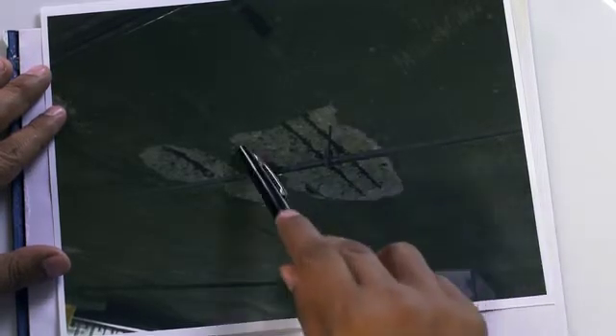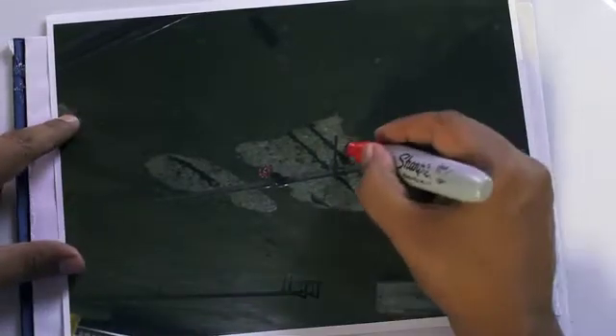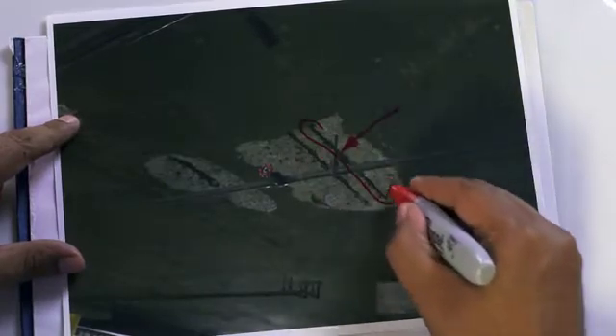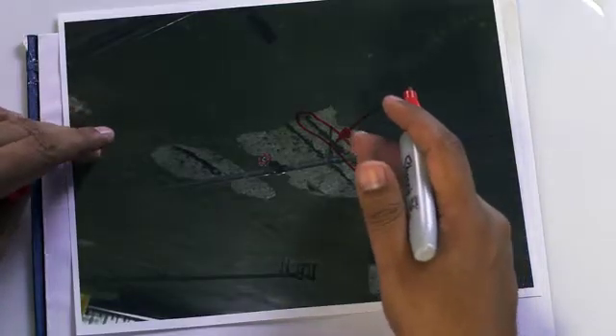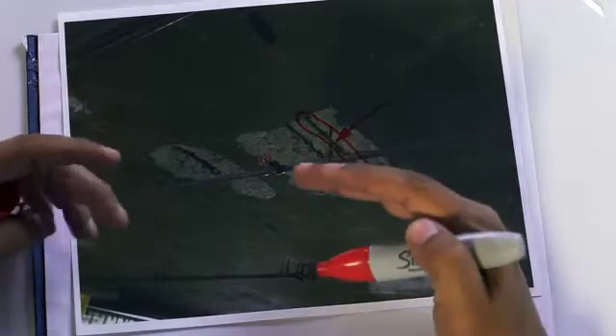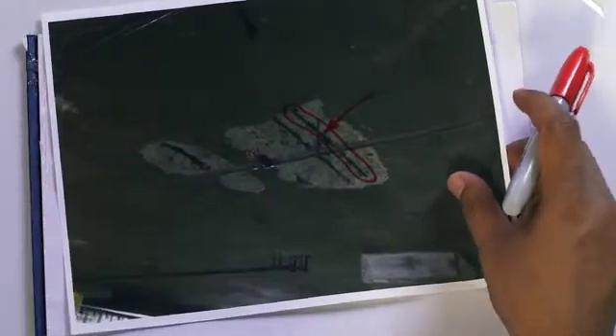So why did I put this class together? Because I'm out looking at these structures all the time, and here's an example. Here's a structure built approximately in the 1970s, and what you can see is a total delamination of the concrete. You can actually see the rebar, and what's happened is the rebar is actually corroding. This is a very dangerous situation because it's happening in the mid-span area, and eventually this rebar is going to delaminate and cause the entire structure to deflect. We've had this situation on multiple structures.